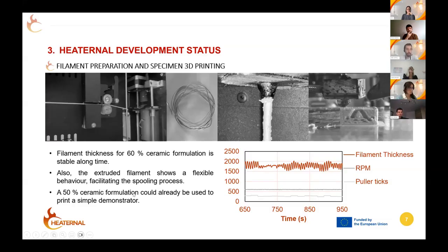Yeah, and it may look simple, but as you saw on the last slide, we have tested up to almost 20 formulations with different polymer percentages, different ceramic percentages, and a variety of additives. Also, we have already used a lower ceramic percentage formulation to print a first demonstrator, as you see in the last picture of the slide.